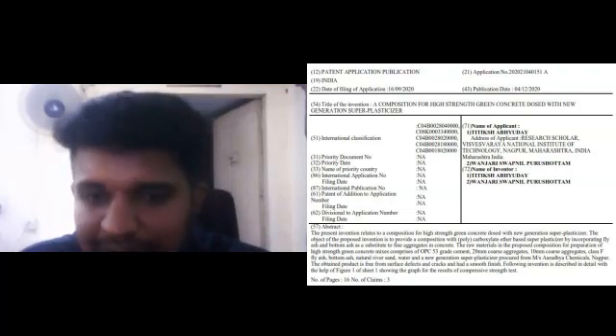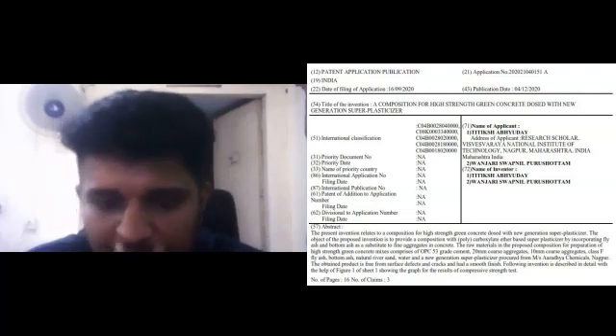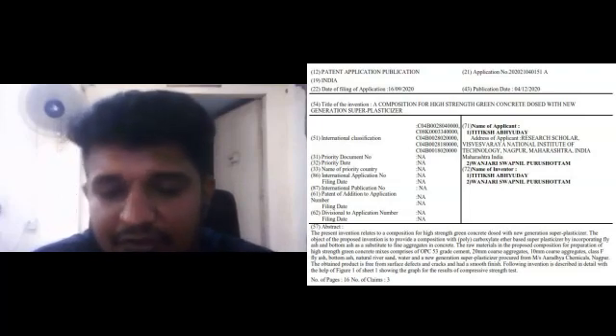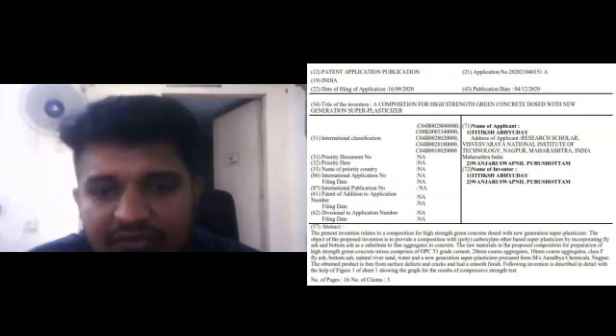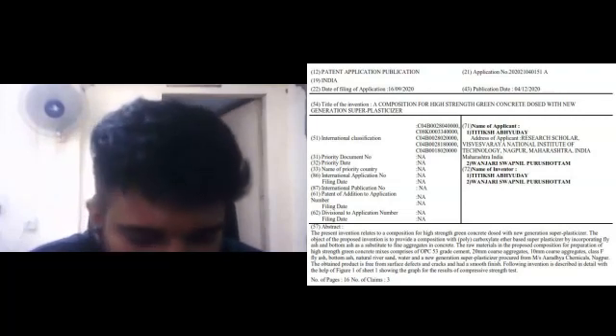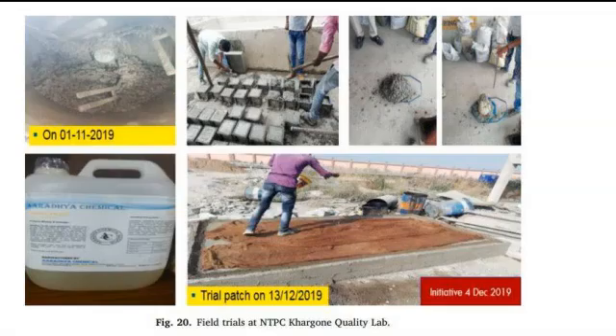However, when you are eliminating the filler material, that is the river sand, you have to use an equivalent product to act as a filler. But when I use fly ash and bottom ash, the overall fine content gets increased almost 3 times. In that case, the concrete loses its homogeneity and its dense interpacking structure. So you have to tweak the mix design a little bit. You have to incorporate a slightly varying proportion of aggregates and so on. And that is what the patent is about. We developed a new mix design and filed a patent for it.